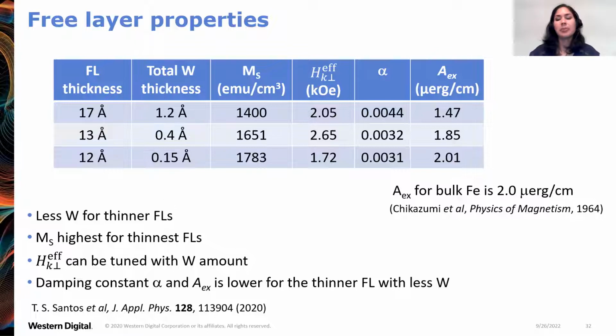Now, your question of what happens if you leave the boron out. No, the question is why don't you directly use cobalt iron instead of cobalt iron boron? Is it that by using cobalt iron boron, and when you leave out boron by annealing, you achieve better epitaxy? So the cobalt iron boron layer that's closest to the MgO layer, you need it to have this boron to achieve this solid phase epitaxy.